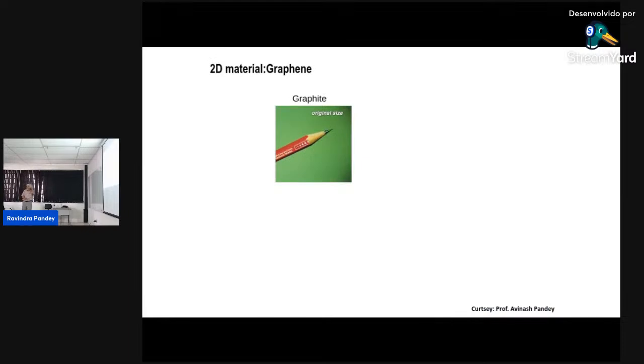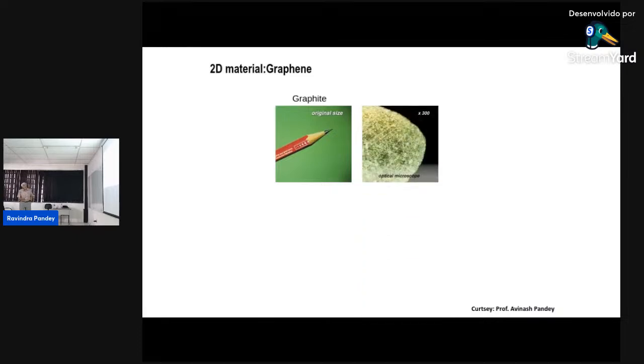This slide I like. If you say graphite is a pencil, nowadays nobody uses it, but the old timers like me have used it. You start magnifying it, it's 300 times in an optical microscope, and you can pinpoint the tip. You can go further down, this is the electron microscope, about 90,000 times, and what you can see here is the surface structure. Further down, we are talking about STM, and you can really image these hexagons, the carbon hexagons coming out of this graphite material. So this is such a powerful technique we have nowadays.